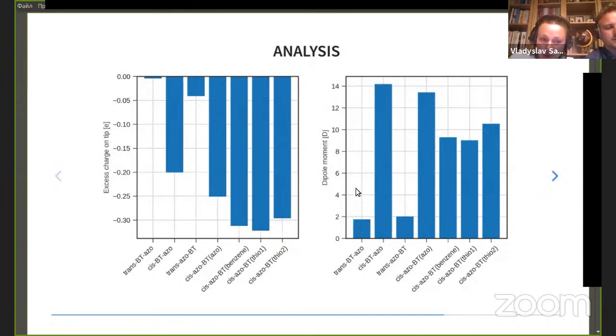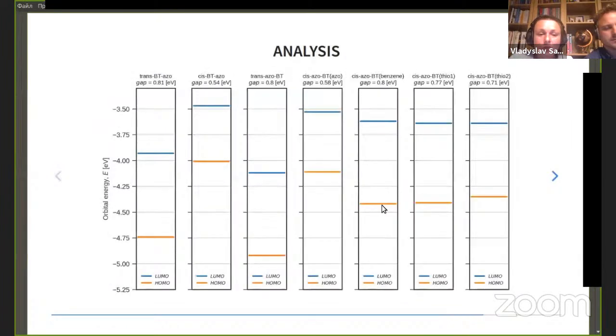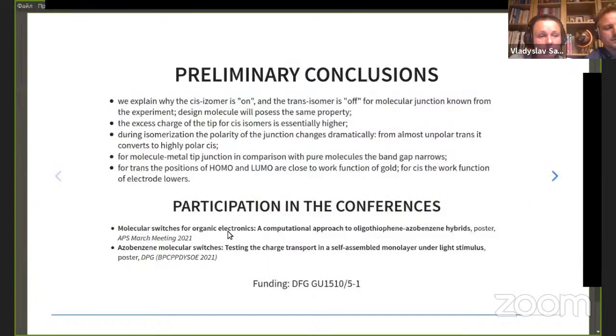Here you see also dipole moment changes, which is also important because in this case we can change the work function of the electrode. If the dipole moment is close to 0, nothing happens. If it changes substantially going from trans to cis under UV light illumination, then we can, let's say, change the work function of the electrode, which is again shown from this slide, which shows the HOMO-LUMO gap. The HOMO-LUMO gap for trans is very close to the work function of the gold electrode, and then it narrows substantially for cis isomers. And preliminary conclusions, which you can read, I mentioned already during my talk.